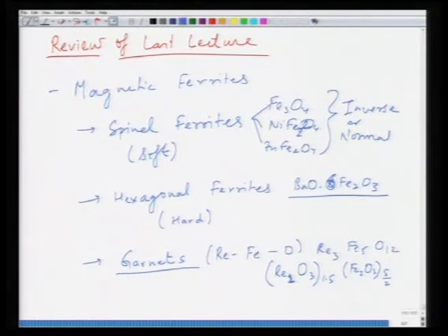So, this is what essentially a garnet is, and garnet can be tuned quite well, because you can use this rare earth atom as either yttrium or terbium or gadolinium or neodymium or lanthanum, and depending upon the magnetic strength of each of these ions, you have a net magnetization of the material, which essentially is nothing but (5 minus 3 mu r) times mu b, or you could write (3 mu r minus 5).